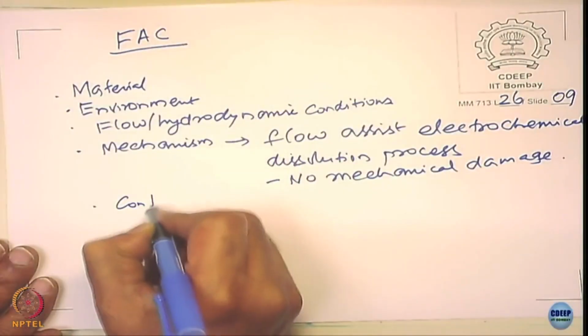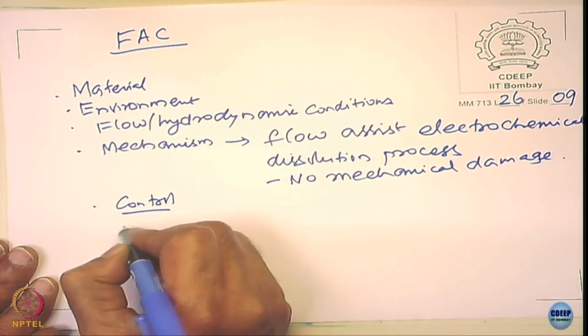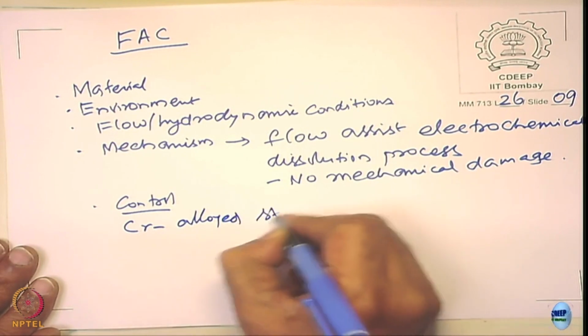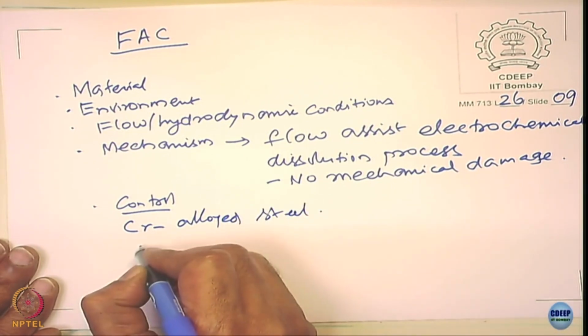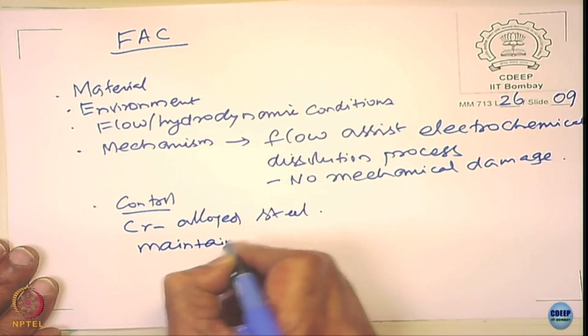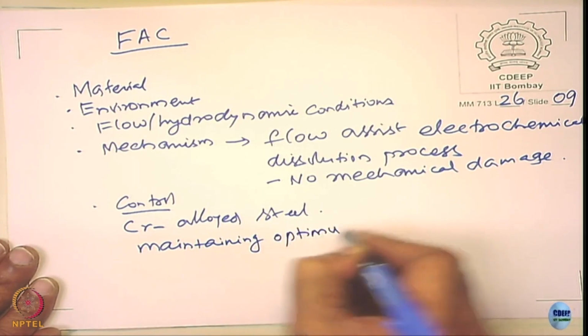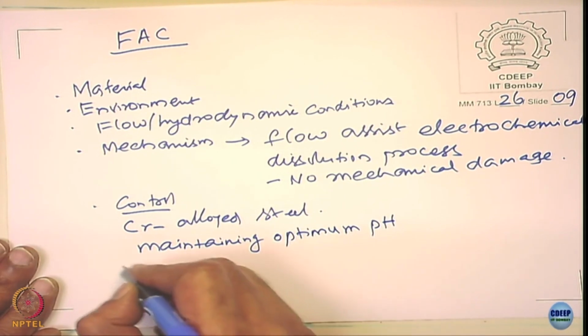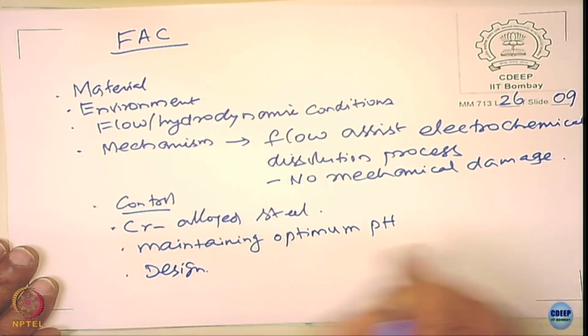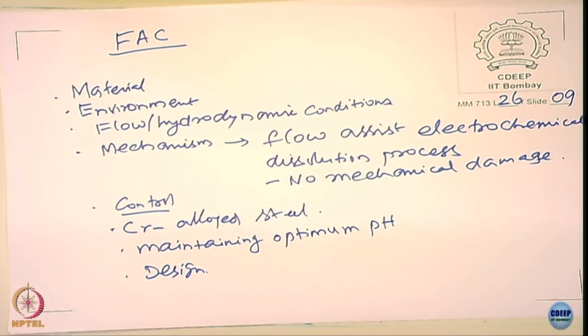How do you control this? Control measures: chromium alloyed steel used. Maintaining the optimum pH. Very important thing, the design, right? Why do you say design? The hydrodynamic conditions existing on the surface depend upon flow conditions, right? So it could change. If you are going to have sharp bends, you are going to have more flow assisted corrosion. If you avoid that, it may reduce. If you reduce the velocity, then also the erosion, not erosion, corrosion, flow assisted corrosion would decrease. So the design of the system also is equally important.